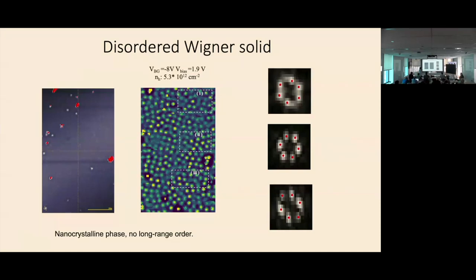We also see there are even weaker disorders, and some of those are oxygen replacing sulfur. This substitution is an isovalent defect, so they are not charged defects. And some people claim that even the vacancies behave more like isovalent defects.